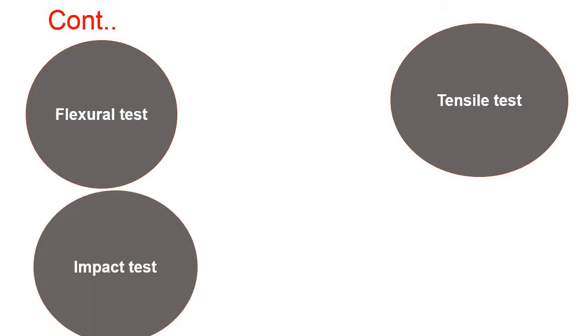In the impact test we are using the ASTM standard D256/10. The dimension of the specimen is 62.5 mm into 12.5 mm into 3 mm. Normally we will go for the Izod impact test. When the Izod impact test is conducted, we have to calculate the impact strength, in which the specimen is mounted vertically against a pendulum hammer with a swinging action.